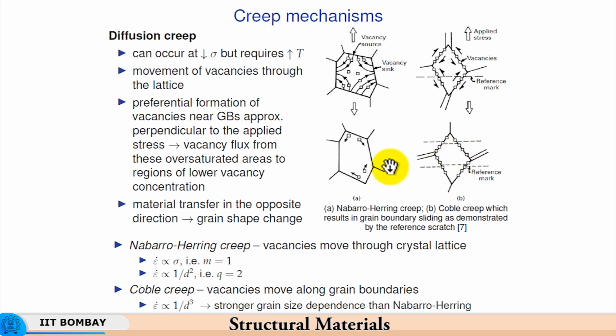The proof that there is relative grain boundary sliding can be gauged from, let us say, two scratch marks. Let us say originally the scratch marks were just made across this. Now, after a certain amount of creep, the boundaries have moved. So, this was a continuous boundary, dotted line. Here it has moved upwards. So, this reference mark has moved upwards as a result of grain boundary sliding. So, you have made a scratch, and then because of sliding this scratch has moved. This reference mark which was continuous has become discontinuous. So, in case of creep related deformation, this discontinuity comes into play.